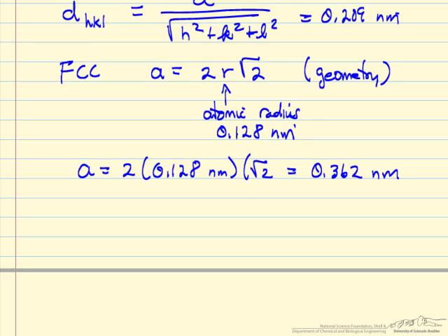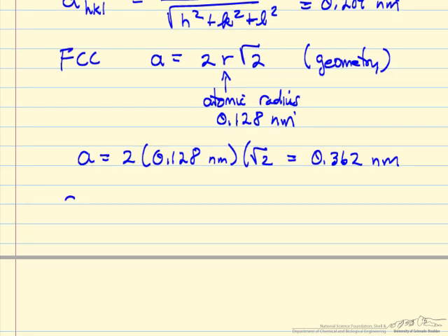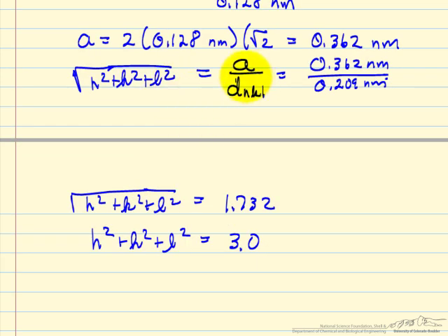Substituting the atomic radius, we now have the unit cell dimension. We substitute that in, and we can calculate the square root of h²+k²+l² equals a over d_hkl. Substituting the calculated values for the unit cell dimension and interplane spacing, we square both sides and get h²+k²+l² equals 3.0.